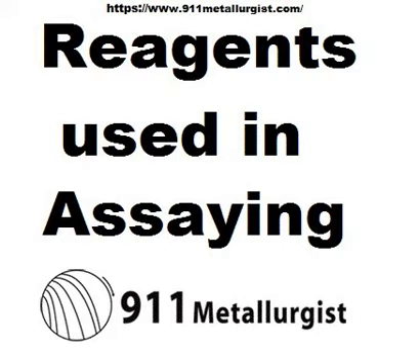The strong acid at ordinary temperature does not act on iron or tin, and in most cases it acts better when diluted. Some nitrates being insoluble in nitric acid form a protecting coat to the metal which hinders further action. Where the strong acid does act, the action is very violent, so that generally it is better to use the dilute acid. When iron has been immersed in strong nitric acid, it not only remains unacted on, but assumes a passive state, so that if, after being wiped, it is then placed in the dilute acid, it will not dissolve. Tin and antimony are converted into insoluble oxides, while other metals dissolve as nitrates.